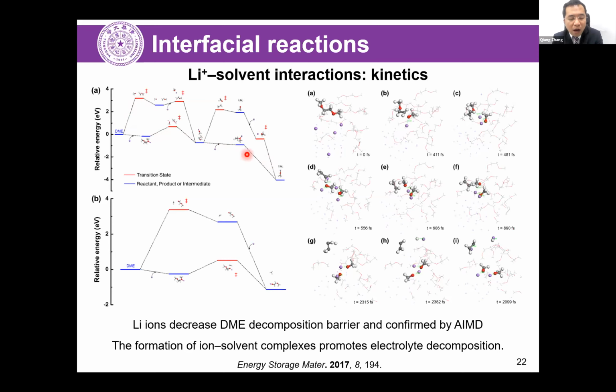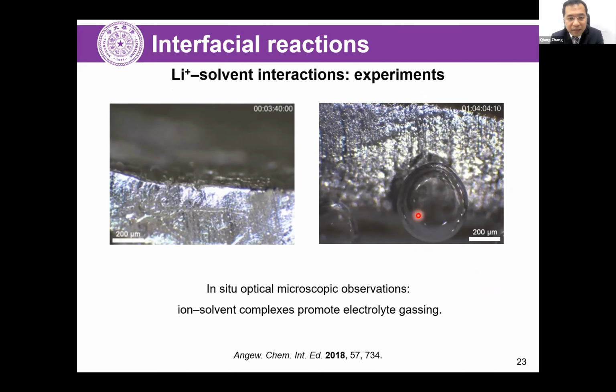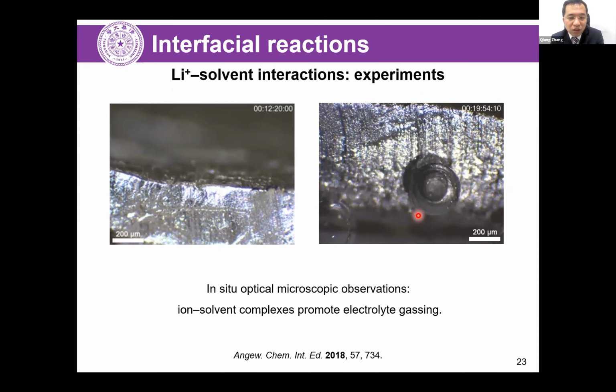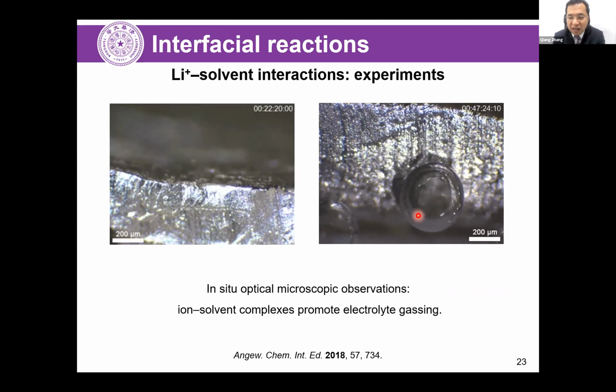So in this case, if we want to stabilize the lithium metal anodes, we have to think how to stop the electron transfer from the lithium metal anode to the ion-solvent complex, and how to retard the interfacial reaction, because from the simulation, it is found that the formation of ethylene happened around 600 femtoseconds. It's a quite fast process, and the only way we can modulate is to reject the electron transfer from fresh metal to the electrolyte. So in this case, we try to observe, is it possible to coat the lithium metal anode with a film to protect the surface?